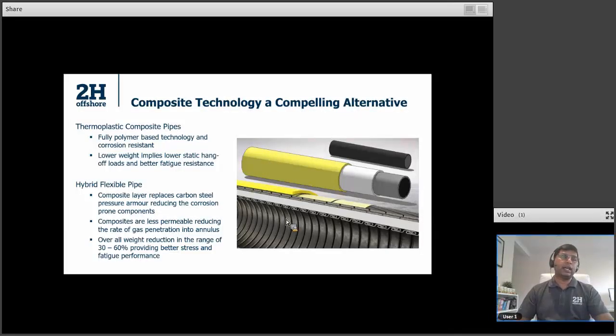On the hybrid side of things, again, we are completely replacing a carbon steel layer with a composite layer, which means we reduce the weight of the pipe and also reduce the permeation, because composite layers deliver a better performance against gas permeation compared to a traditional polymer structure, and will provide you a better strength by minimizing the rate of corrosion. So with this in mind, we can definitely, to some extent, mitigate the corrosion aspect completely, or in a hybrid case, we can definitely reduce the nature of corrosion and hence make sure that we reach the required field life for the desired application.